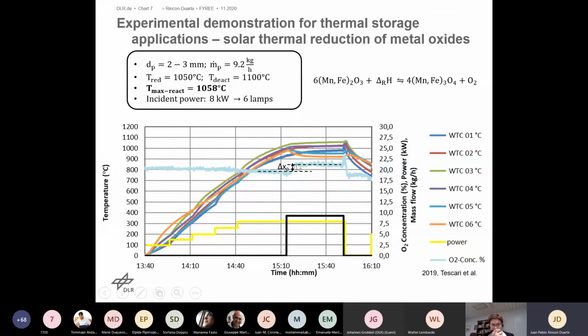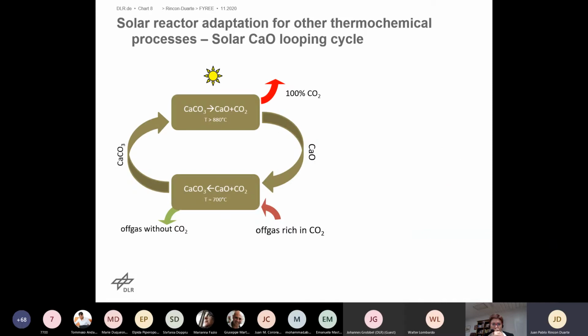If we take a look at the signal of the oxygen, after some minutes, we observe that the oxygen concentration in the gas flow increased. That was an indication that we were already performing the reaction. We did several experiments, and we could demonstrate the feasibility of this reactor to run this continuous process.